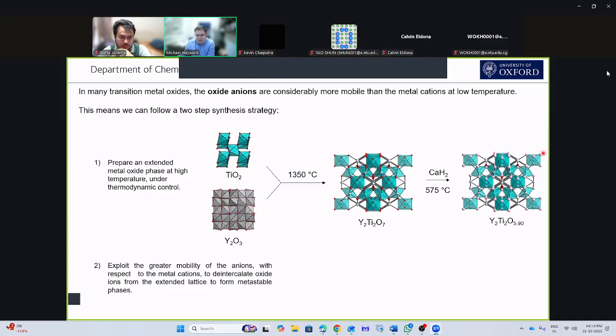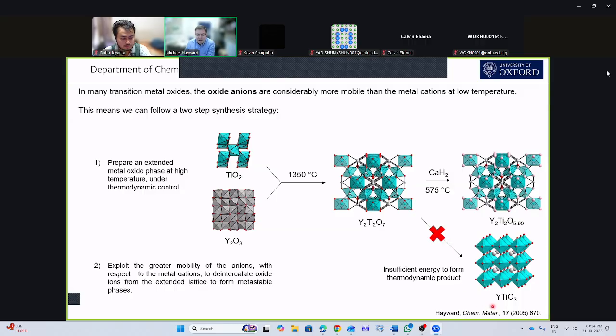And this is a metastable titanium 3+ compound that I can't make directly by combining any combination of titanium and yttrium oxides. And we know that this is a metastable phase because the thermodynamically stable phase with the same composition has the perovskite structure. So by adopting this two-step strategy, where in the second step we use the higher mobility of the oxide ions, we can make highly metastable materials.